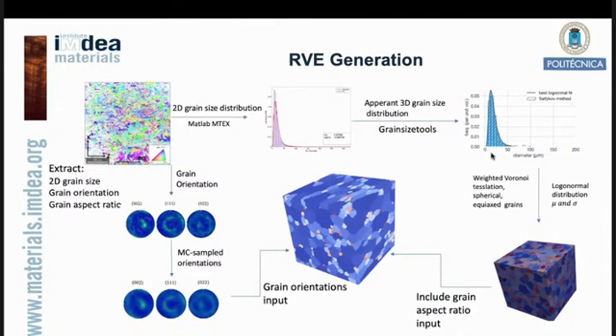When we get the apparent 3D grain size distribution, using weighted Voronoi tessellation for spherical equiaxed grains and log normal distributions of the grains, we are able to build an RVE which has spherical equiaxed grains. But in general, we need the elongated grains, so we include an artificial aspect ratio of the grains as per the actual microstructure. And secondly, we use the orientation. Since the actual microstructure has millions of grains, we use Monte Carlo simulation to sample the orientation, and then we include it into the RVE.